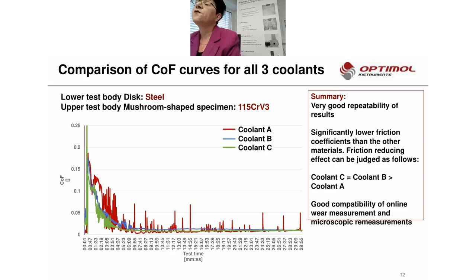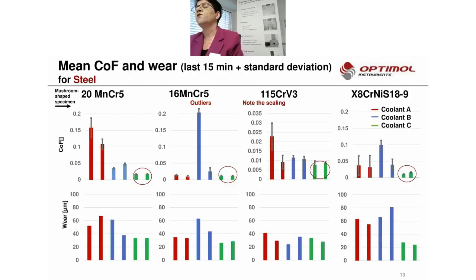And the 115CrV3, which is a very, very hard and very good typical tool material. All three have very good low coefficient of friction values, but the most stable one is again C, and B would also be a good one. And as we calculate again to see the repeatability, you can see how the repeatability is really given with this method.